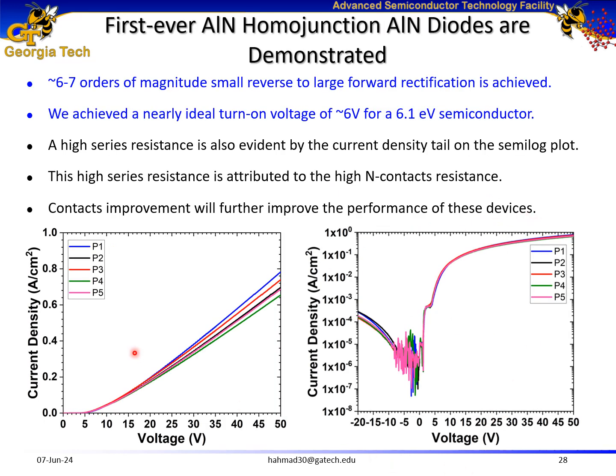In this slide, I've shown the JV characteristics, both forward and reverse bias, for these homojunction aluminum nitride diodes. I achieved approximately 7 orders of magnitude rectification for these diodes, and we achieved a nearly ideal turn-on voltage of approximately 6 volts for a 6.1 electron volts semiconductor.